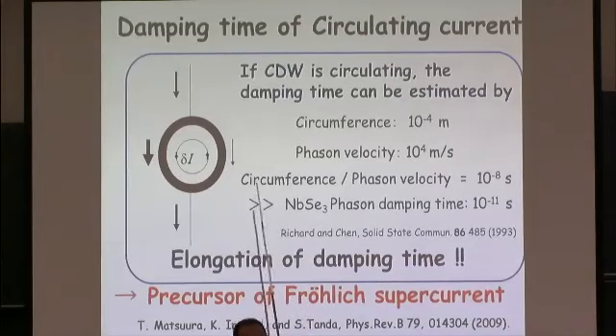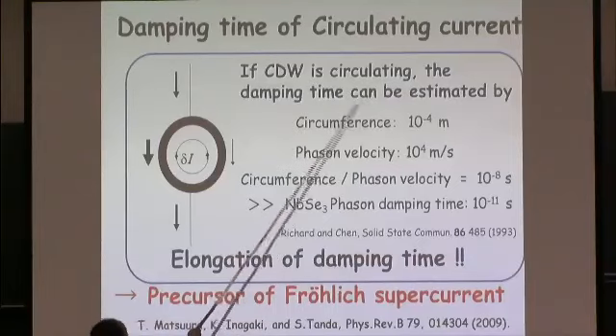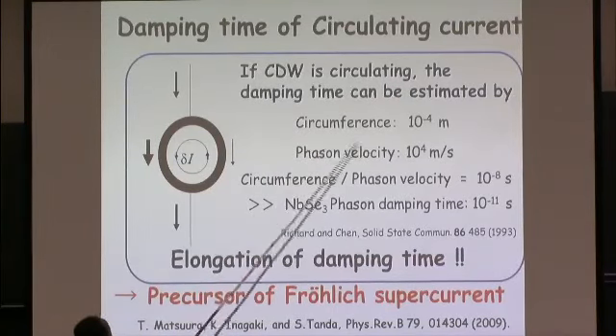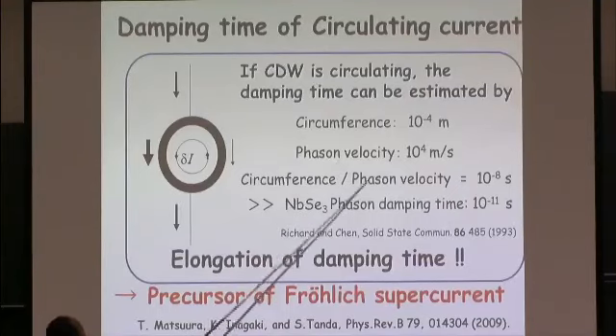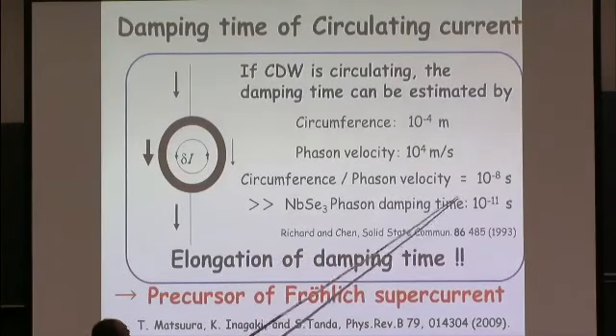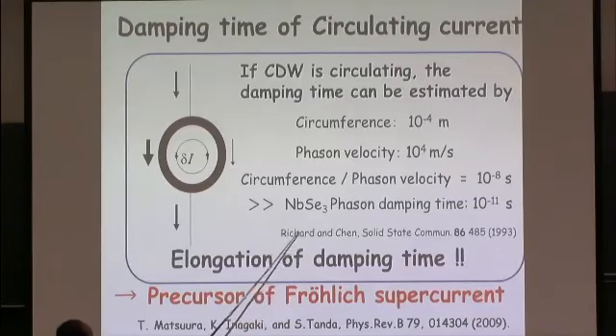We estimate the damping time of circulating current. If the charge density wave is circulating, the damping time can be estimated by circumference 10^-4 over phason velocity 10^4, circumference by phason velocity, 10^-8. It means the NbSe3 phason damping time is less than 10^-11. It's an elongation of damping time. It means a precursor of Fröhlich supercurrents.